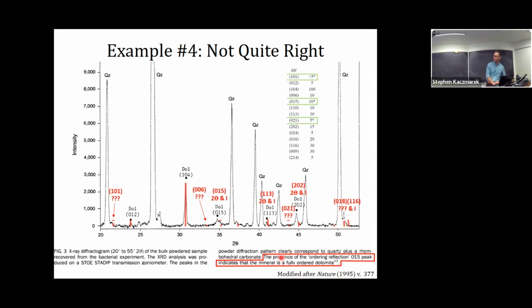But here's the claim: the presence of the ordering reflection, the 015, indicates that the mineral is fully ordered dolomite. And like I said, this peak is too high actually to be the 015. It doesn't work that way.